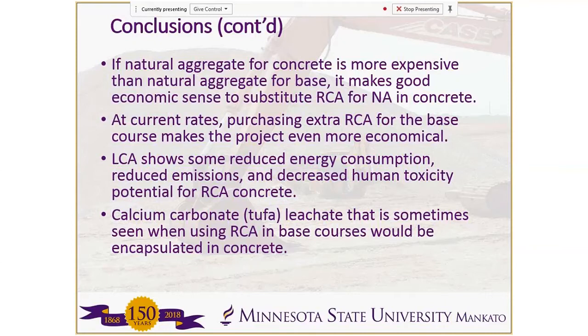We found that at current rates, you can purchase extra RCA for a relatively cheap price. That makes the project even more economical. Using life cycle analysis, we showed that there's some reduced energy consumption, reduced emissions, and decreased human toxicity potential for the RCA concrete. Also, it's pretty widespread to use RCA in the base course, but some places are reporting problems with leachate, calcium carbonate, which is called tufa, when this is used in the base course. So if you use the RCA inside the concrete, that will tend to decrease this problem because it will be encapsulated within the concrete.